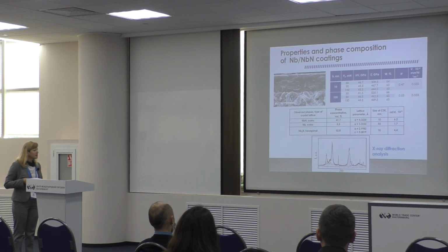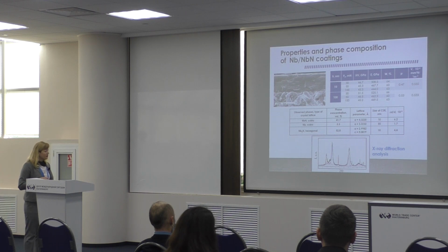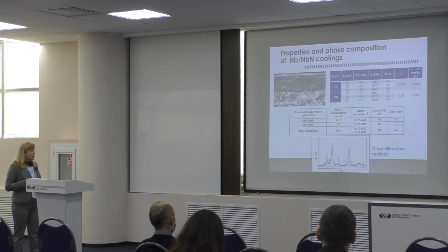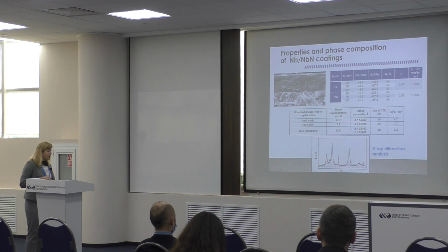By X-ray diffraction analysis, we showed that the multi-layered coatings have the following phases: niobium nitride with cubic crystal lattice, niobium, and niobium 2 nitride. But the coating has only 5.5 volume percent of niobium phase. It means that in the metal layer we have not only the metal phase, but also a nitride phase with lack of nitrogen.